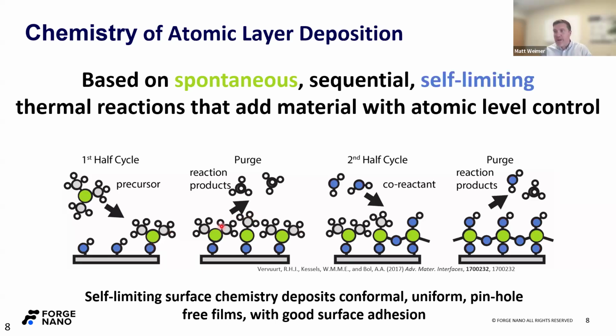The one last thing I'll point out on this slide is once you get that full monolayer of TMA on the surface, now the surface looks like a bunch of methyl groups, which looks a lot like TMA. So once this surface looks like itself, that reaction stops. This is where the self-limiting nature of ALD really comes out. Just for completeness, the second half cycle here is water, but we do the same chemical reaction where we're removing a proton and generating methane. Just as a brief aside, methane as a reaction byproduct is pretty benign, right?